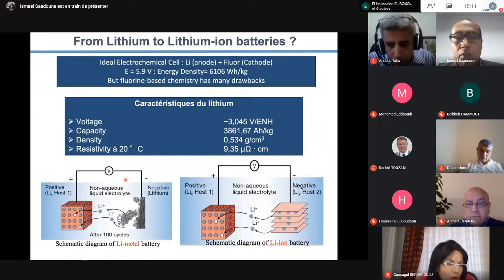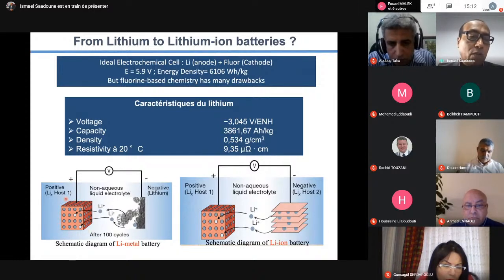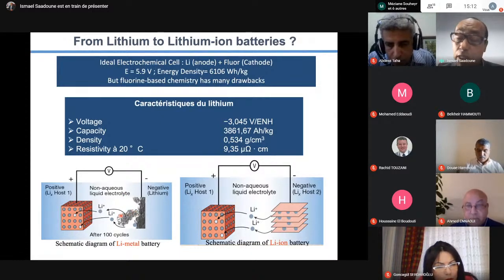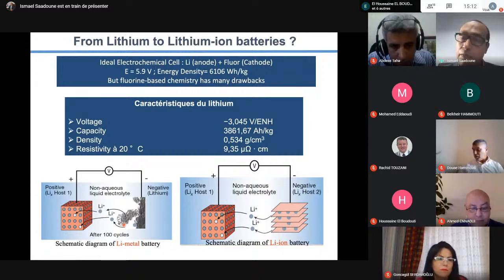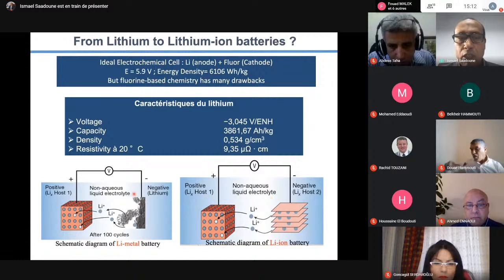People started to work on lithium batteries many years ago, in the 70s and 80s. The cell consists of one positive electrode material and lithium foil. Lithium foil is a very homogeneous foil. When starting to charge and discharge, we start to see this evolution of what we call dendritic growth. It's lithium metal growing during cycling, and if it grows, it can short circuit between cathode and anode material, leading to fire.